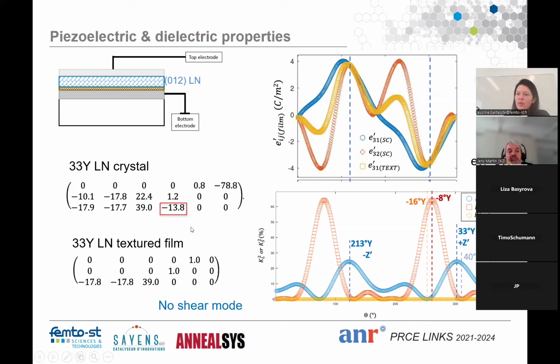But on the other hand, when you have this textured film, we add additional symmetry, and some coefficients will go close to zero. So for example, the e34 coefficient becomes zero in textured films, and this coefficient is what gives a shear wave in single crystal films. In a textured film, shear waves will never be excited because this coefficient is zero in this Y33 orientation. Here I put the shear coefficients. We have longitudinal coupling, what I have been talking about, in blue, and S is for shear waves. So 3,5 is always zero, even for a single crystal. But 3,4, for example, if you take Y33 orientation, you will still have a little bit of coupling for the shear wave.